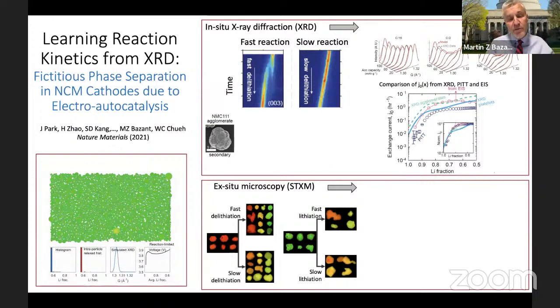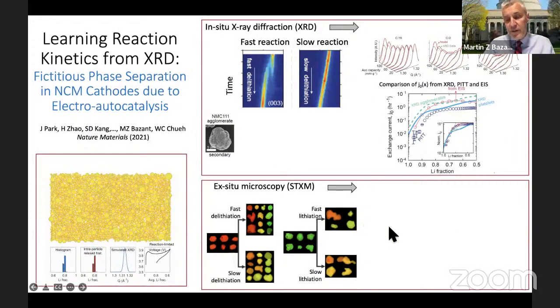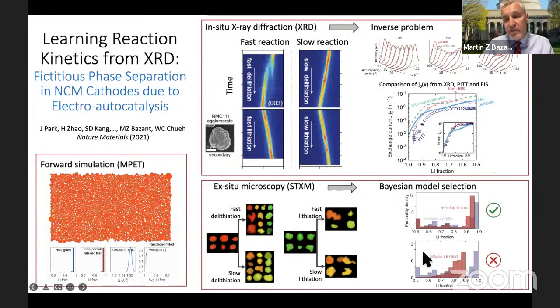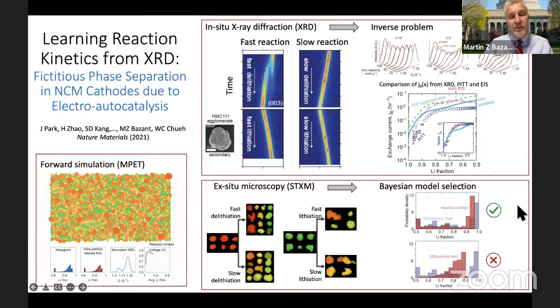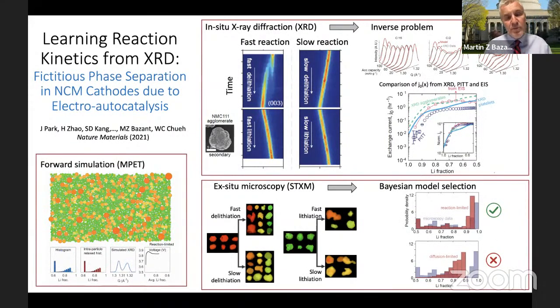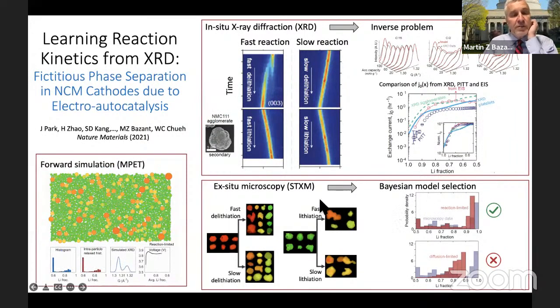But that's not what we find, because it is driven by reactions. We find what I call Mosaic Instability. The particles just sort of snap into their stable phases, and they all have different concentrations from each other. And so that's verified there. And we actually did a Bayesian analysis to show that the reaction limited model was the only one that could explain this data. So I think this is actually a much simpler system than lithium iron phosphate. So we were able to get much more definitive results out of this one.